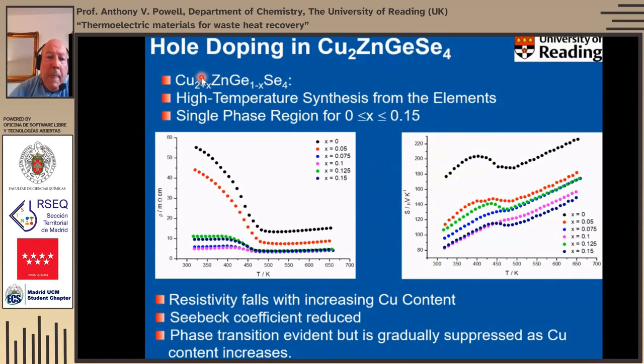into our structure. What we see then as we increase that hole concentration, the resistivity falls. And also, of course, there's a corresponding fall in the Seebeck. And although the phase transition is still evident, you can see that it's gradually being suppressed. And we think that's because there have been some calculations that suggest that the copper defect formation energy is increased as we make copper-rich phases. So it becomes more difficult for those copper ions to delocalize and for that copper sublattice to melt partially.